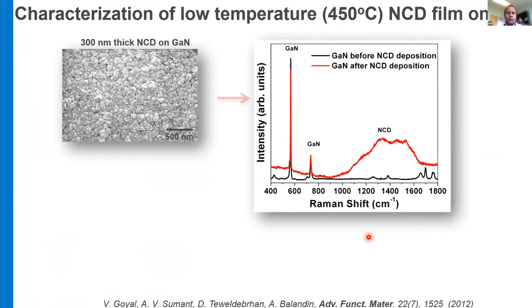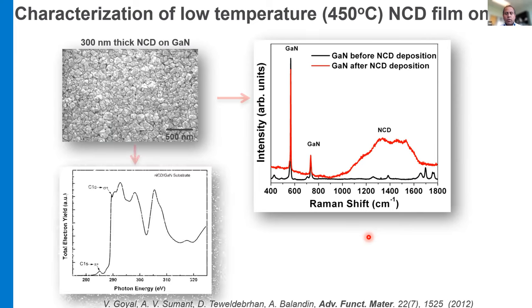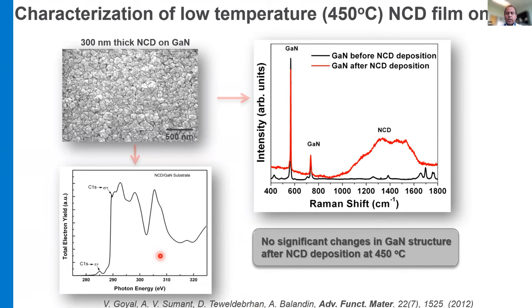So in this case, it's very important to check whether the gallium nitride has decomposed. So we used Raman spectroscopy before and after the nanocrystalline diamond deposition. And then you can clearly see that the gallium nitride peaks are pretty strong even after the nanocrystalline diamond deposition, indicating the gallium nitride lattice is preserved. And then we also did NEXAFS spectroscopy just to see the quality of the diamond by using the pi star peak and the sigma star. You can clearly see that it's a very high quality diamond with more sp3 bonded carbon. So we did not see any significant changes in the gallium nitride structure where the nanocrystalline diamond deposition was done at about 450 degrees Celsius.